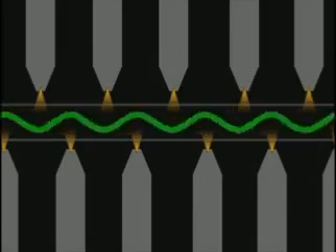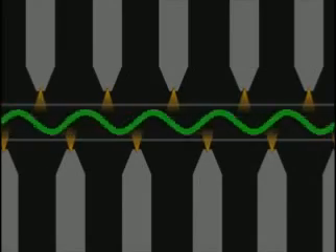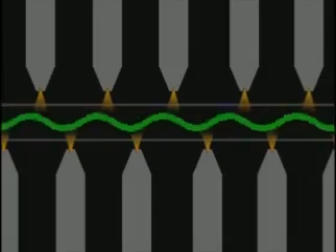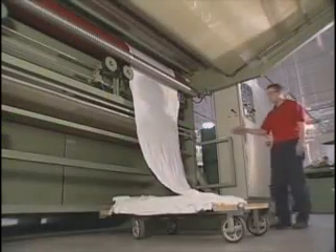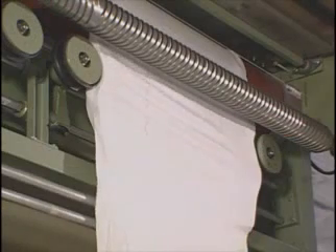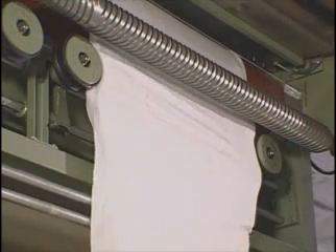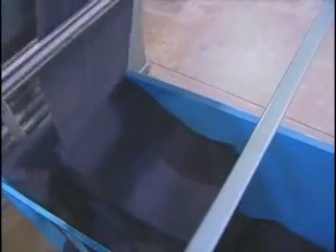5. A flow uniform in intensity, varied in direction, but not offsetting in application. 6. Spreading of the fabrics with overfeed at the entry of the dryer or at a station just prior to the dryer. 7. Maintaining sufficient overfeed in all drying zones to allow for complete mobility in the fabric length during deswelling. 8. Tension-free precision plaiting of the fabric for apparel manufacturing or for the next processing step.